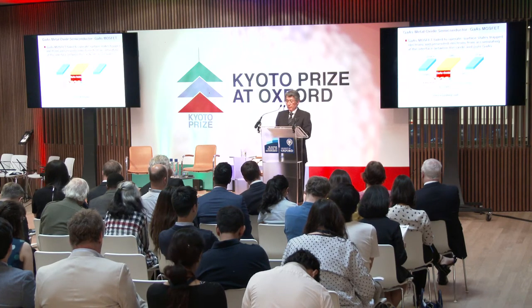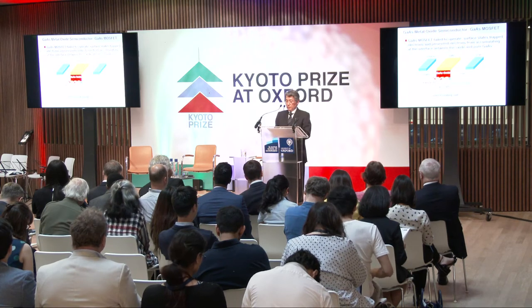Since I was directly engaged in a desperate struggle with the gallium arsenide surface state. This is because, as I mentioned earlier, no electrons accumulate in gallium arsenide MOSFETs due to their surface state. Gallium arsenide and aluminum gallium arsenide in the modulation doped superlattice showed similar characteristics in the crystal structure, and at the surface state of those crystal interfaces, electrons could be accumulated.